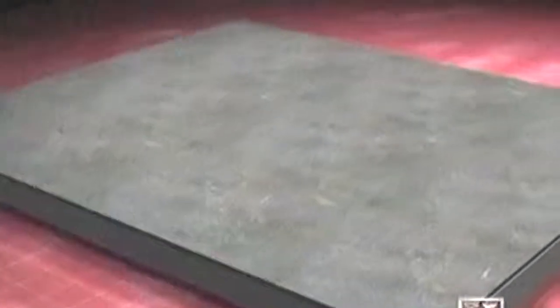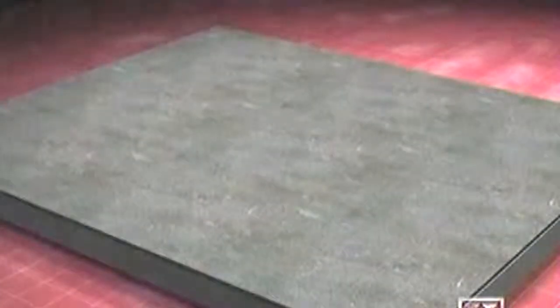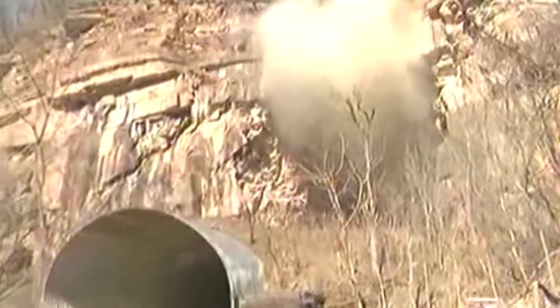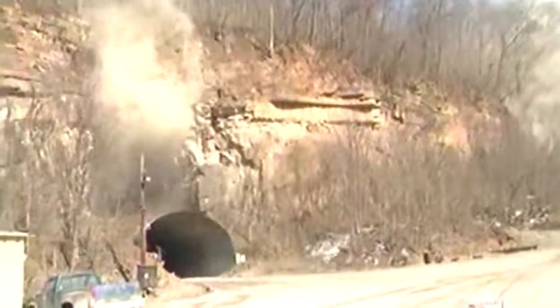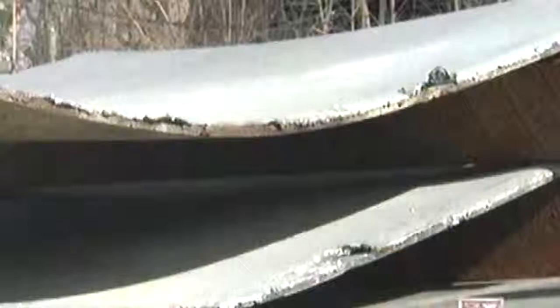As the backer and cladder collide, the weld is created nearly instantaneously across the entire surface of the plate. Because of the intense dust created by the explosion, workers can't retrieve the newly formed clad from the explosion chamber for more than 18 hours. Not surprisingly, the power of the explosion can cause significant deformation to the newly formed clad. Therefore, upon its return to DMC's central processing facility, the clad undergoes a final series of corrections.